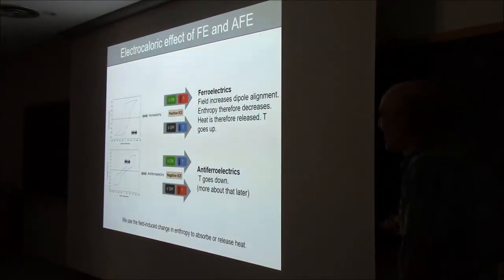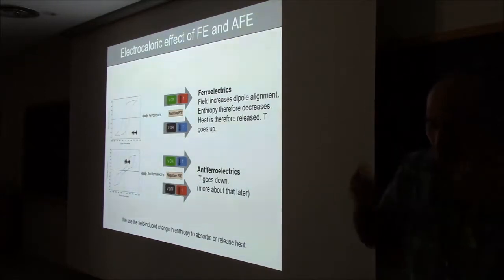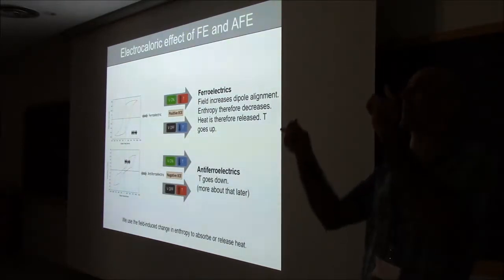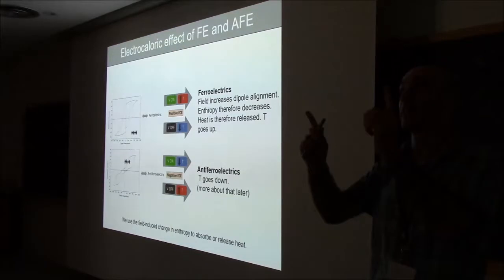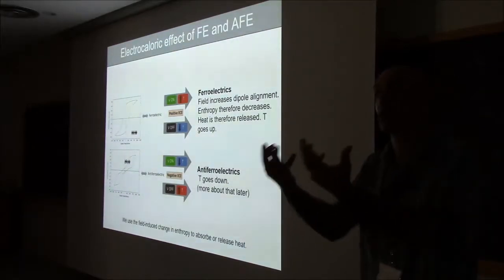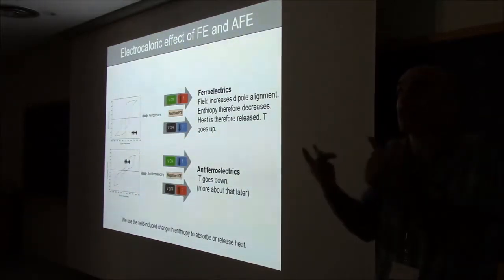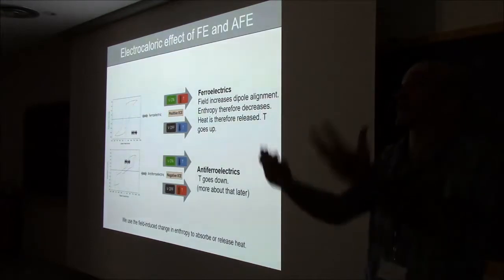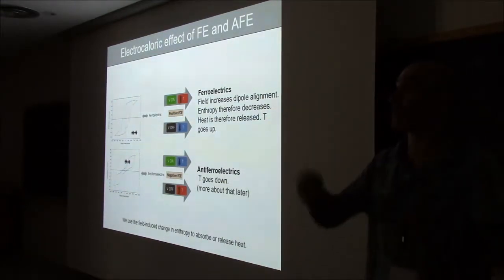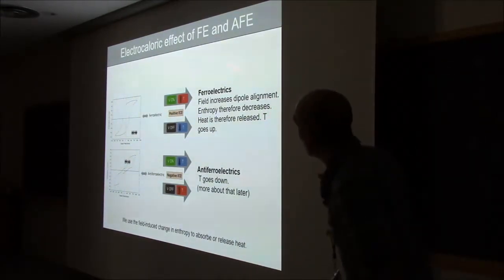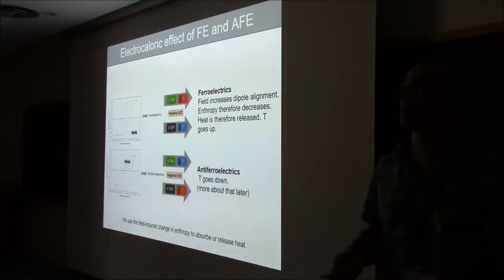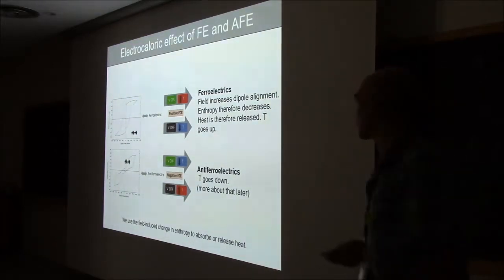In a ferroelectric, or any material, in a polar material, if I apply an electric field, I can align the dipoles. If I align the dipoles, I reduce their entropy. And if I reduce their entropy, they will release heat. So the material will become hot. I apply voltage, things become hot. That's the normal electrocaloric effect that you see in ferroelectrics.